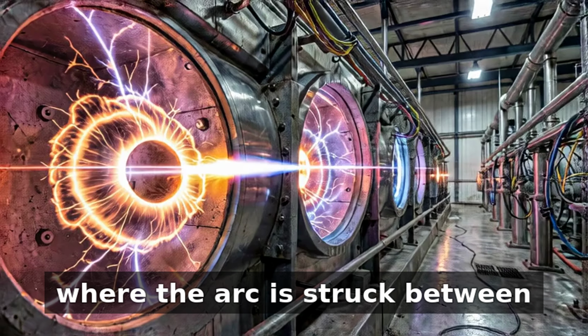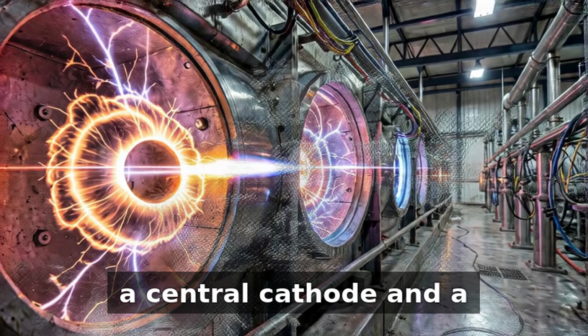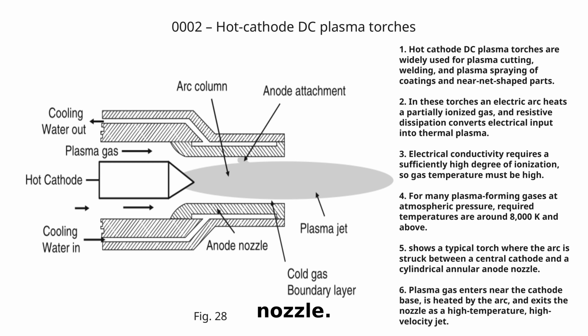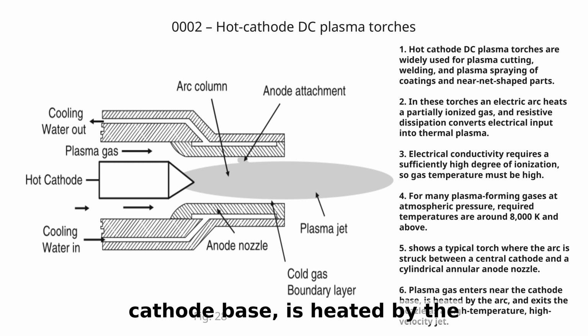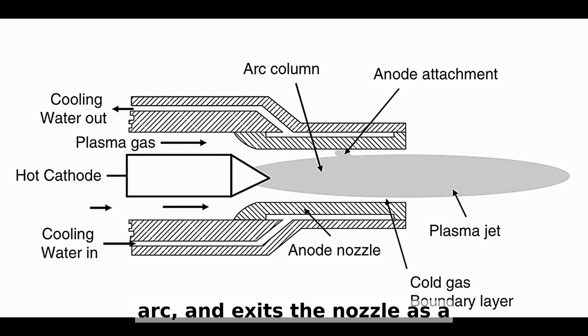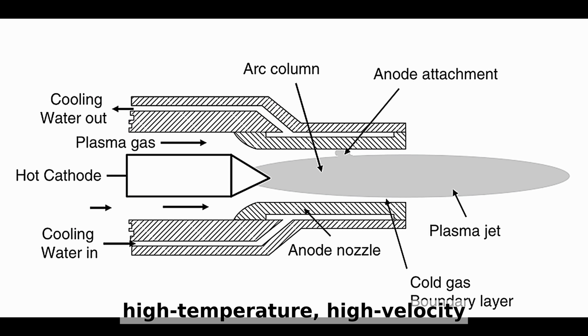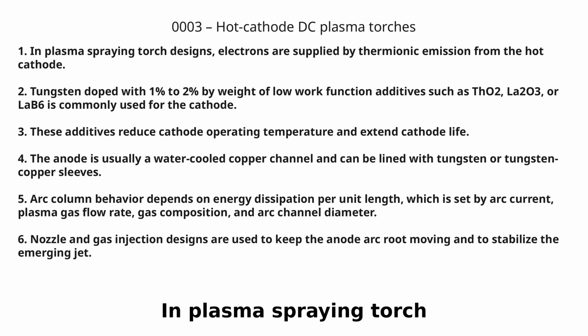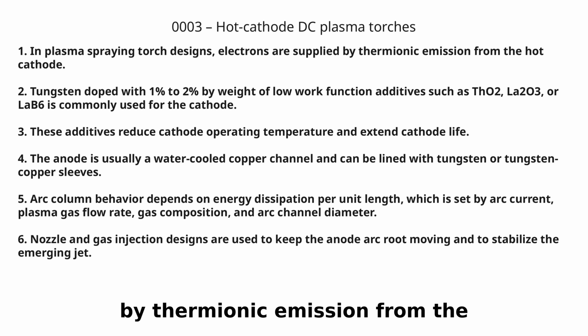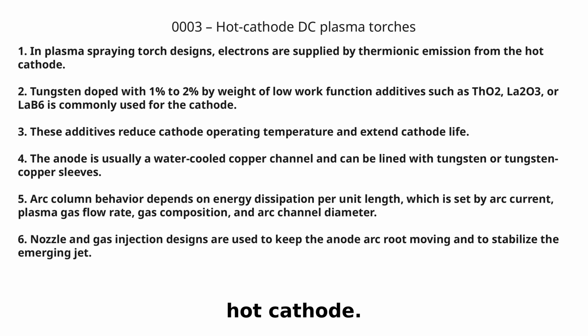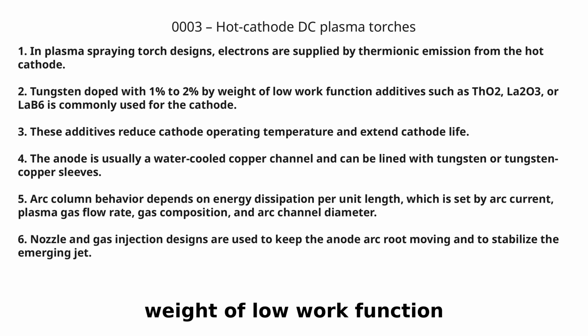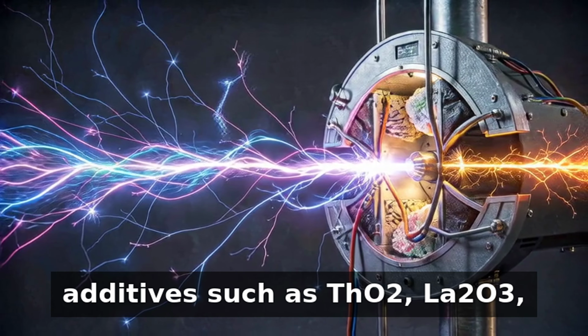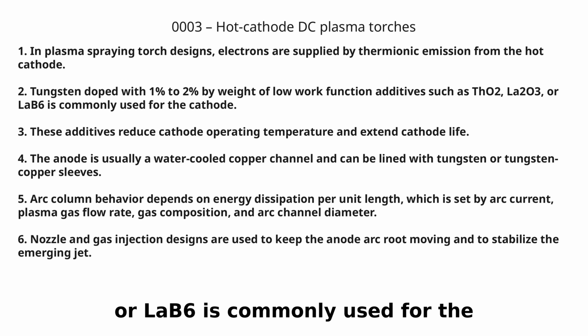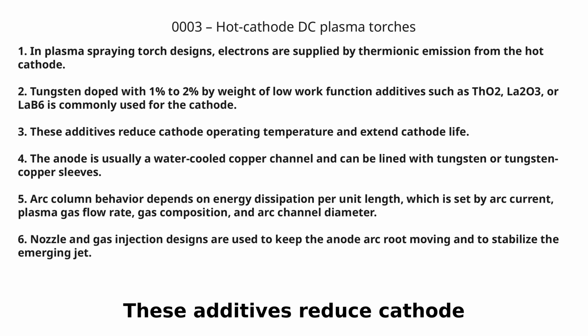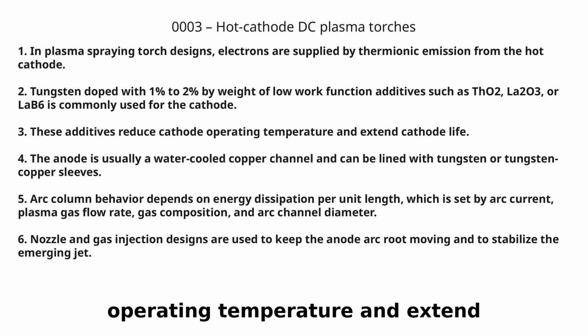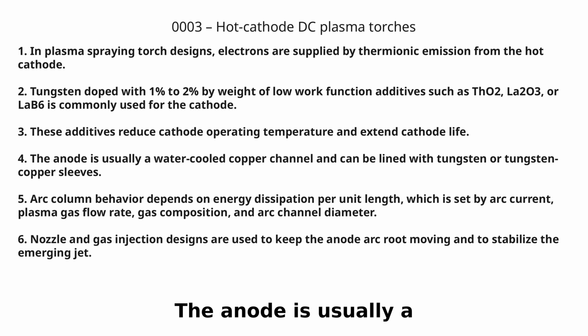Figure 28 shows a typical torch where the arc is struck between a central cathode and a cylindrical annular anode nozzle. Plasma gas enters near the cathode base, is heated by the arc, and exits the nozzle as a high-temperature, high-velocity jet. In plasma spraying torch designs, electrons are supplied by thermionic emission from the hot cathode. Tungsten doped with 1% to 2% by weight of low work function additives such as thorium dioxide, lanthanum oxide, or lanthanum hexaboride is commonly used for the cathode. These additives reduce cathode operating temperature and extend cathode life.